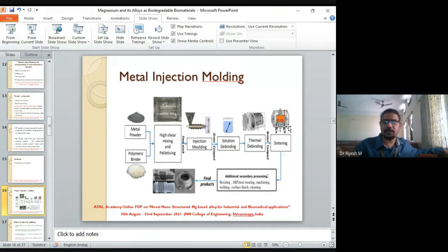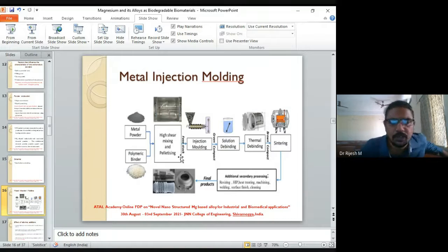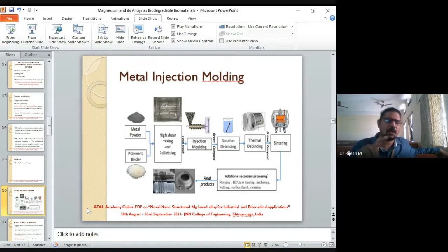You control the sintering temperature and the sintering time. Additional secondary processing like machining, welding, etc. can be carried out here. So you get a final product out of metal injection molding. Metal injection molding is basically a powder metallurgical route where you get the component. The advantage of going for a powder metallurgical route and not casting or a rod product is that you control the porosities.